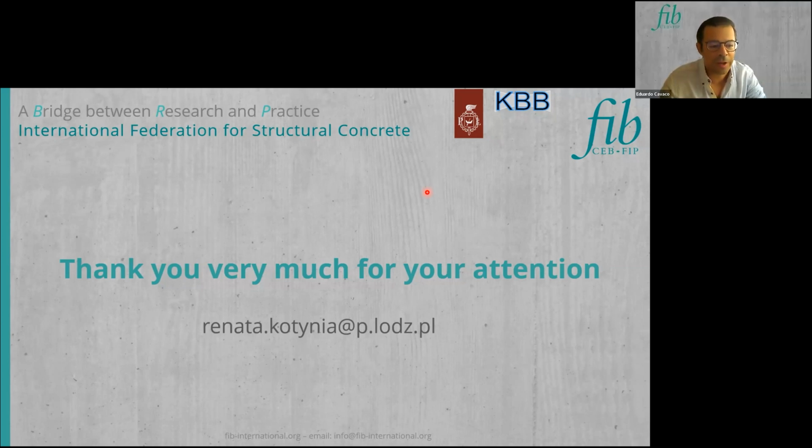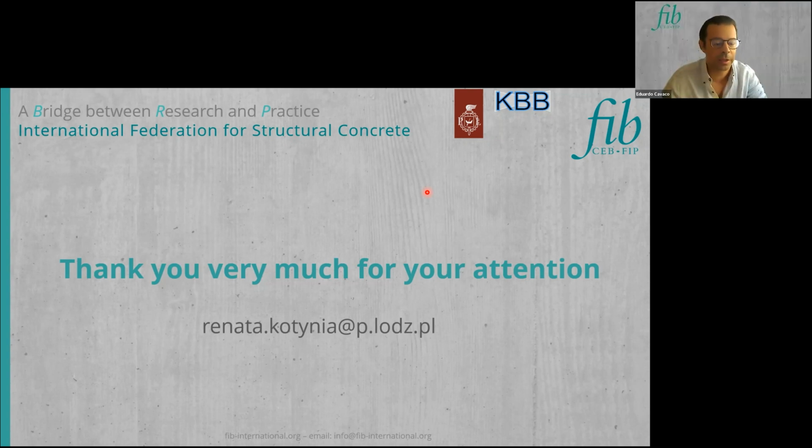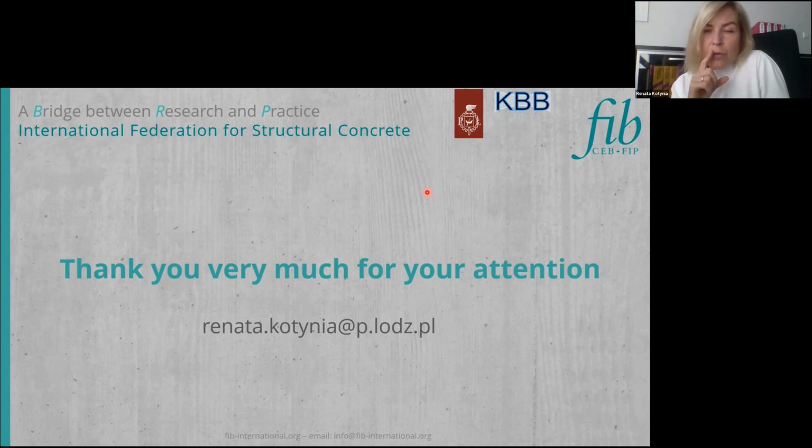Okay, thank you. We have one more question from Firas Shalash. What about the fire protection? Yes, I suggested in one slide that the most effective technique for fire resistance is application of mortar and application of the fibers, not the resin, because the glass transition temperature of the resin is very low. So if it is important to apply this strengthening technique with fire protection, the use of mortar is mostly recommended.